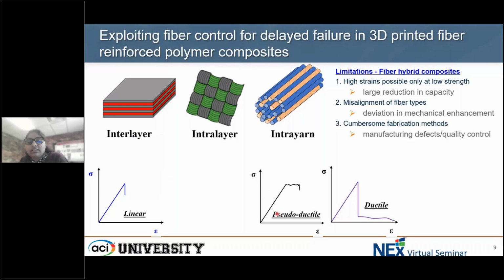We have pseudoductility, which is a flat-topped stress-strain curve of a monolithic tensile test setup, and a ductile behavior that offers the strength needed but also prolongs its failure to a higher strain. But the limitations of these fiber hybrid composites were found to be that there are high strains possible, but only at low strengths. There is therefore a large reduction in capacity, though they can offer those high strains, something like this.